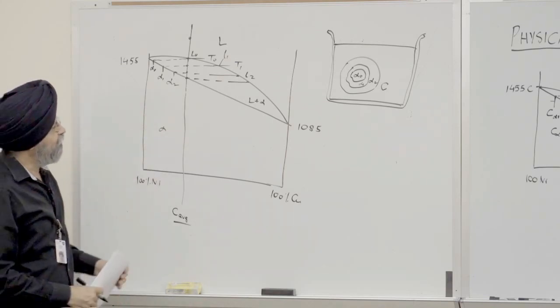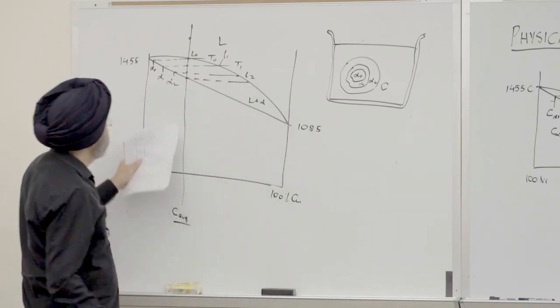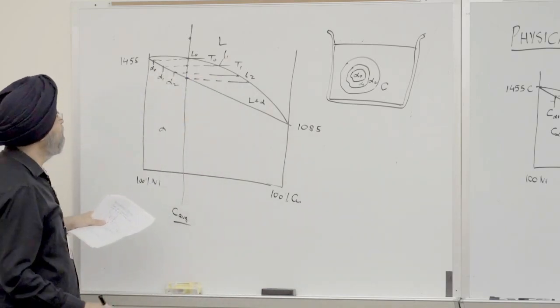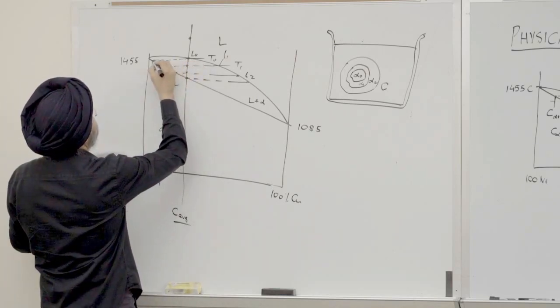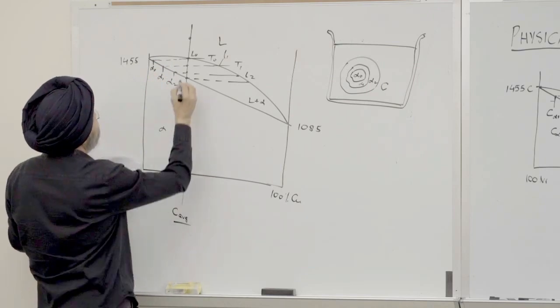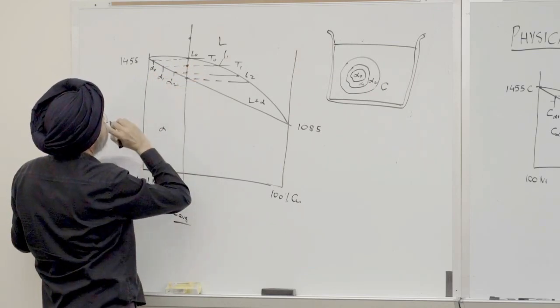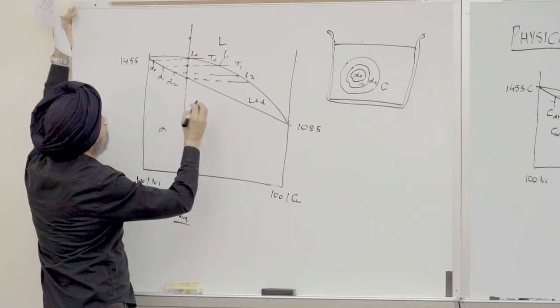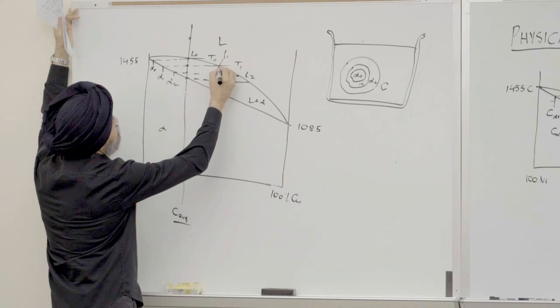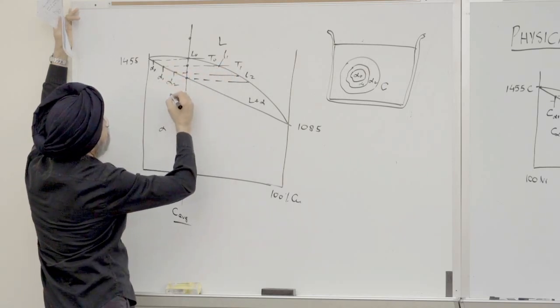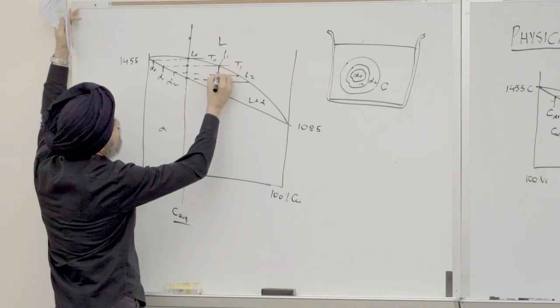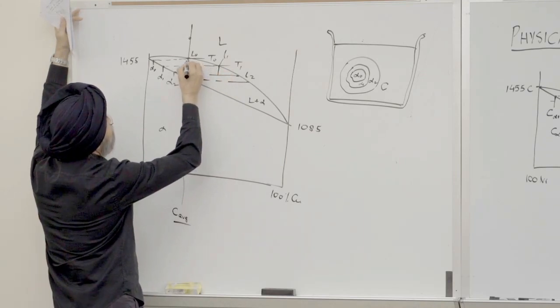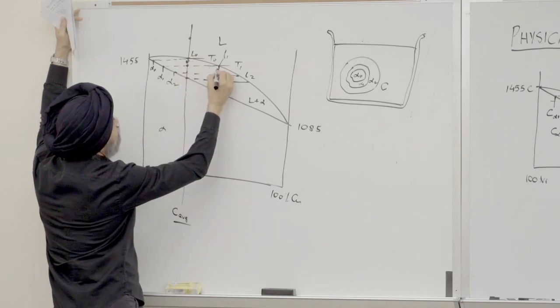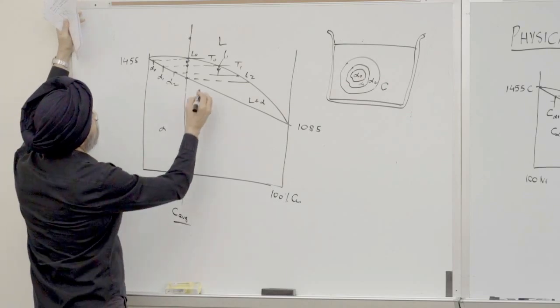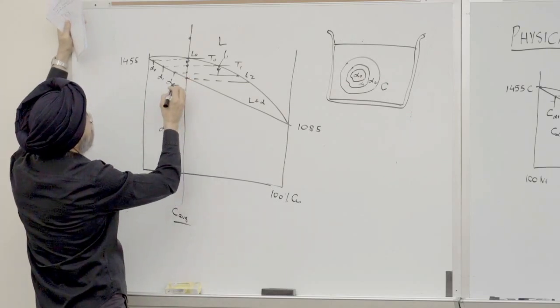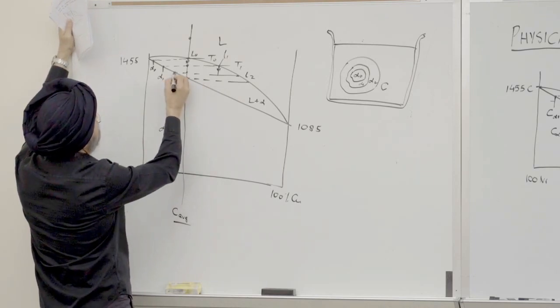So what really happens is, the alloy doesn't freeze like I described. At this temperature, it is true alpha naught came out, right? At this temperature, this is the composition of the liquid, and this is the composition of the solid. So now it's this liquid that is freezing. So we came here, and from here, we didn't come down here. We are now coming down over here. So this is the composition of the solid coming out over here.